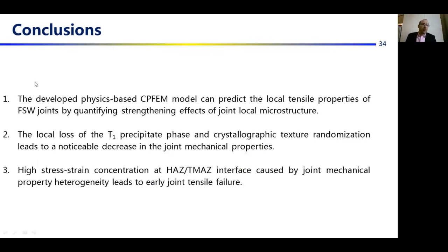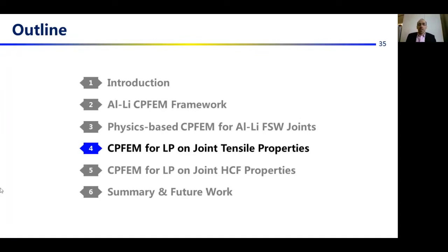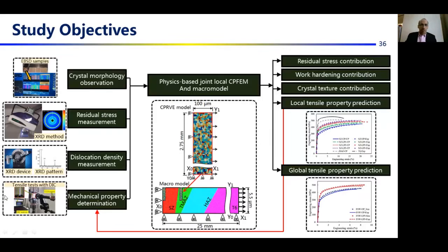For the overall conclusion, the developed physics-based CPFEM model can predict the local tensile properties of FSW joints by quantifying strengthening effects of joint local microstructure. The local loss of T1 precipitate phases and crystallographic texture randomization lead to a noticeable decrease in joint mechanical properties, and high stress-strain concentration at the HAZ-TMAZ interface caused by the joint mechanical property heterogeneity leads to early joint tensile failure. Now the CPFEM for laser peening effects on joint tensile properties.